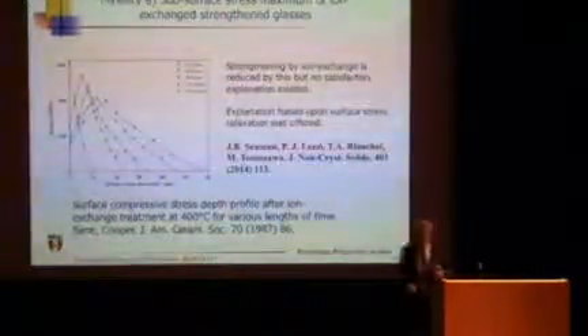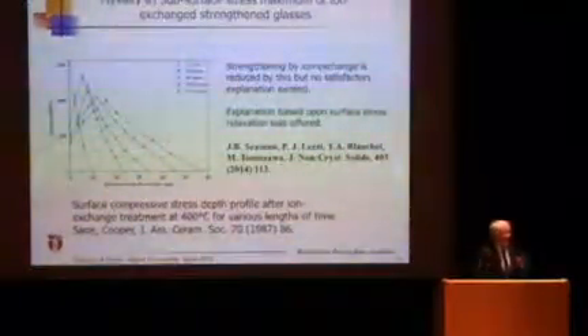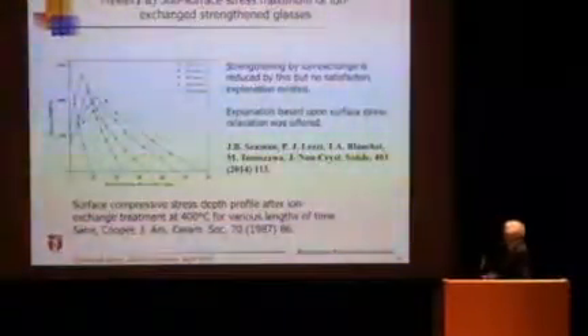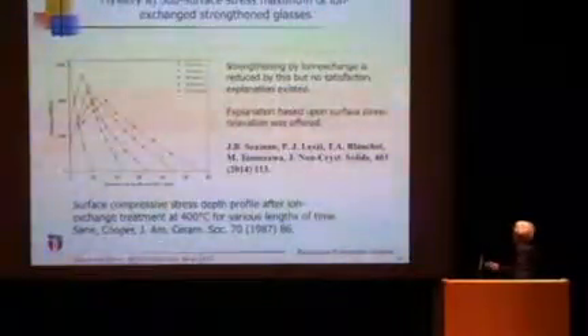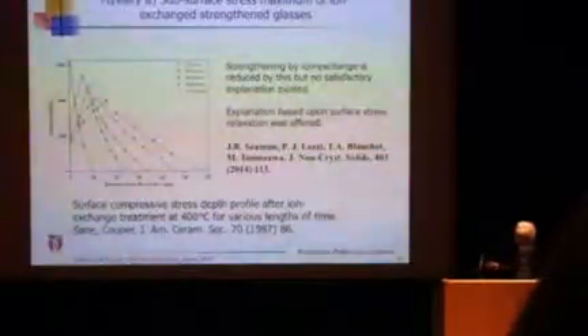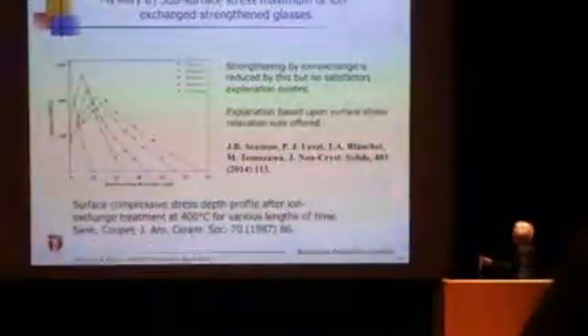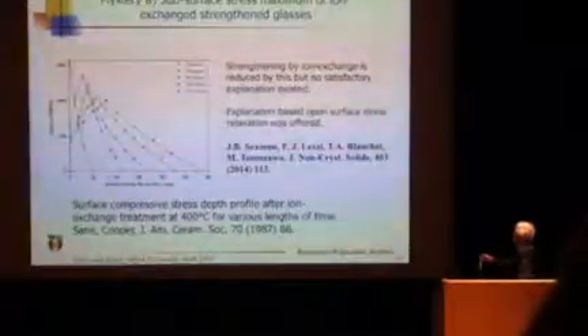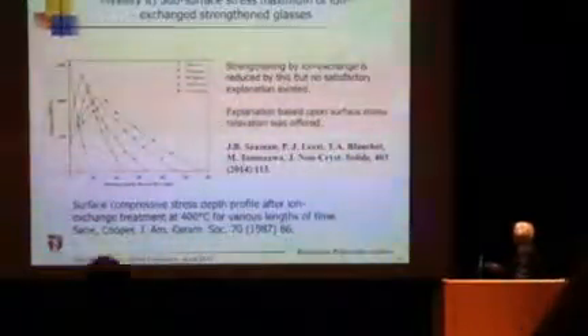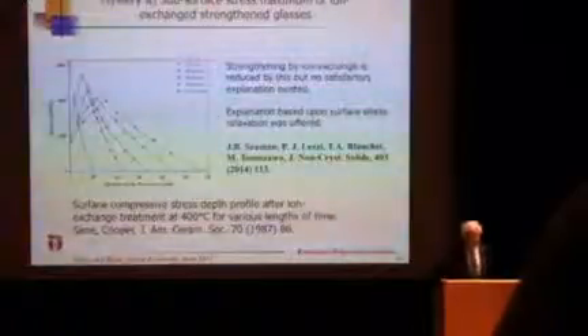Now this phenomenon we found, faster surface stress relaxation, I realized can also be used to explain a couple of mysteries we have known for many years. One mystery, as I mentioned, is that if you do ion exchange, you normally get a compressive layer with high surface compression, and with deeper diffusion during ion exchange, oftentimes the surface compression comes down. Ideally it should go higher and higher, but surface stress is coming down and it's getting deeper with treatment time at constant temperature. This type of phenomenon has been observed for years, but there was no good explanation.